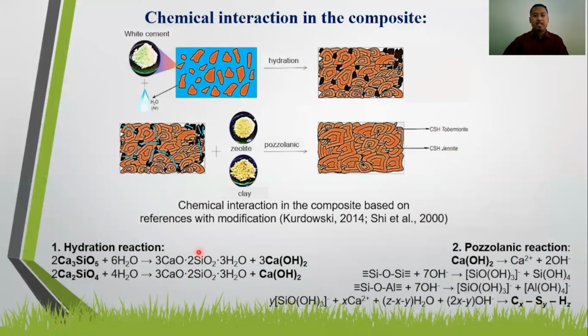Chemical interaction prediction in the composites depends on the hydration and pozzolanic reaction. In the hydration reaction, both tricalcium silicate and dicalcium silicate react with water to produce primary calcium silicate hydrate and calcium hydroxide or Portlandite mineral. Then, in the pozzolanic reaction, the calcium hydroxide reacts with the aluminosilicate compound of the zeolite clay composite to form secondary calcium silicate hydrate. This calcium silicate hydrate affects the physical strength of the composite.